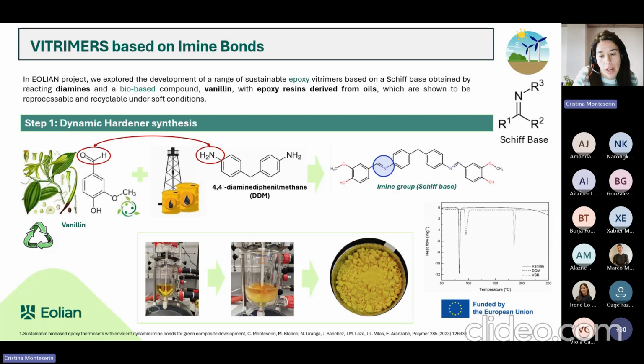Traditionally, this reaction relies on petrochemical-derived aldehydes; however, more sustainable alternatives can be employed. In our case, we are using vanillin, which is a bio-based aromatic aldehyde, obtained from, for example, lignin or other renewable sources, and can effectively replace conventional aldehydes in the synthesis of these Schiff bases. We can obtain this hardener as a powder, in this example with a high melting temperature.